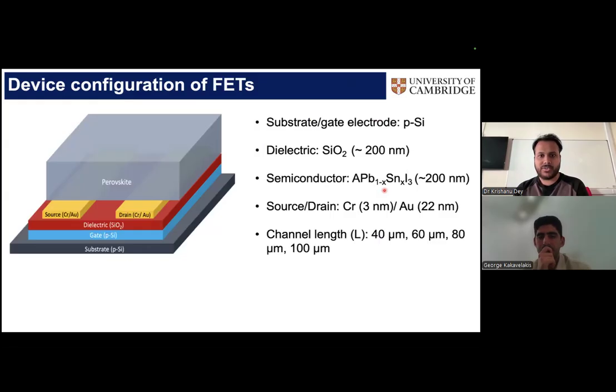So in my research, this is the configuration of the field effect transistor I used. It's a 3-terminal device with a gate, source and drain electrode. The transport happens between the source and drain electrode, and you build the channel, a conducting path for carriers, by applying a voltage at the gate terminal. So that's how it works. These are the materials that I used for the different layers. The perovskite semiconductor is what forms the channel material, and I deposited it in the last step of the fabrication.